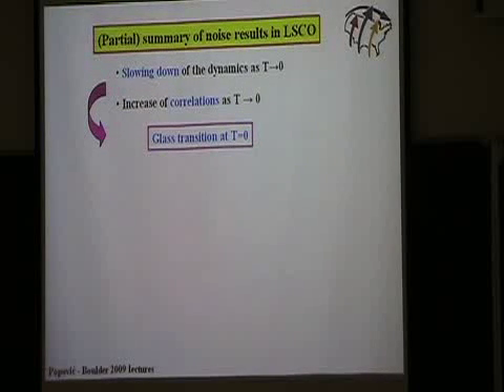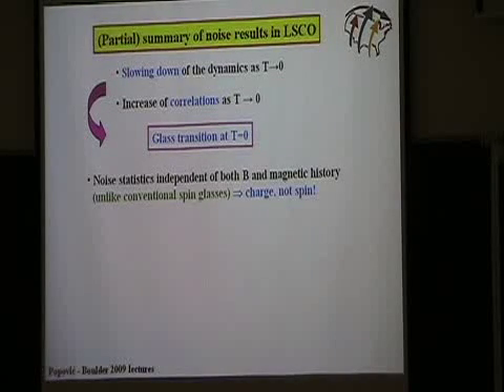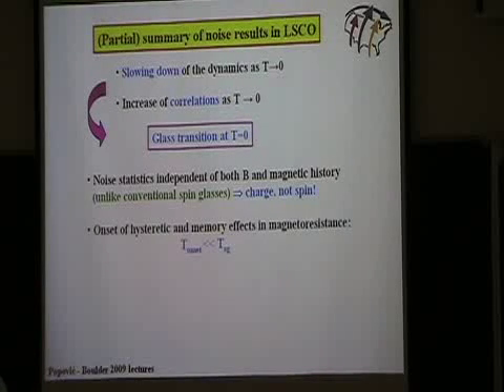So what we conclude from the noise data is that we see slowing down gradually of the dynamics as temperature goes to zero, increase of correlations. So this suggests that there is a glass transition at zero temperature. And the fact that the noise statistics is independent of both B and magnetic history, which is very different from what happens in conventional spin glasses, suggests strongly, I think, that this glassiness is due to the charge and not spin degrees of freedom. And this is further supported by the fact that also